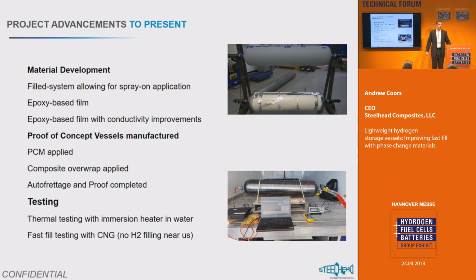This was only about 2 months ago, about 4 years later. We took it to a CNG filling station and tried it out. And the results were good. We weren't seeing the 20%, but we were in the high single digits, and we haven't optimized it all yet. It's kind of cool. It's kind of an interesting project.